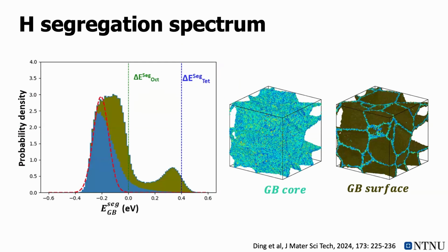It's very clear that the typical interstitial sites, tetrahedral or octahedral, have fixed segregation energy. The grain boundary, depending on its type and structure, has a Gaussian-like distribution of segregation energy. What we can conclude is that most of the segregation energy in the grain boundary is lower than at the octahedral sites. That's why when hydrogen enters the material, it prefers to stay in the grain boundary region rather than at the interstitial sites.